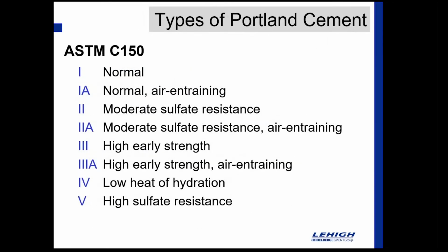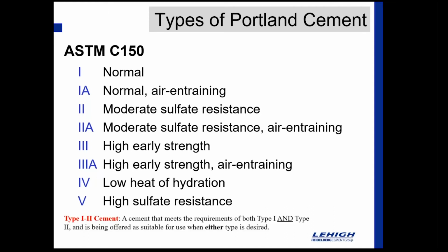And so within C150, there's 8 main types of cement, and we also have, in addition to that, type 1-2 cement. So we have type 1 cement, which would be called the normal cement, type 1A, normal air entraining, type 2, moderate sulfate resistance, type 2A, moderate sulfate resistance, air entraining, type 3, high early strength, type 3A, high early strength, air entraining, type 4, low heat of hydration, and type 5, high sulfate resistance.